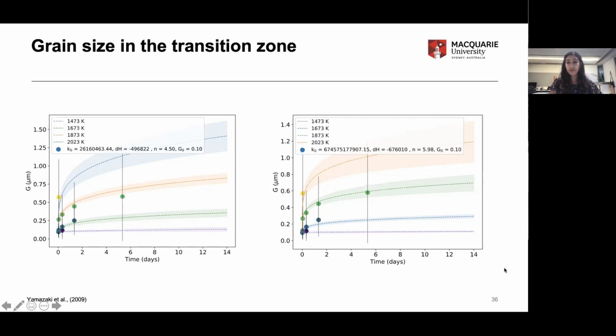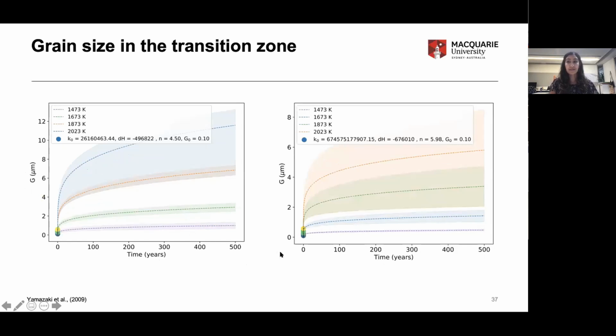For a period of 14 days, the data looks great. As soon as we start to extrapolate that out to 500 years, again, we have the same problem. Although the order of magnitude of the grain size isn't too different, we have no idea what that temperature and pressure is doing, and we're overlapping again just for a period of 500 years. So for people using these grain growth kinetics to try and understand things like mantle viscosity and the evolution of Earth over 4 billion years, we need to really constrain the kinetics before we start using them in models to predict mantle viscosity, for example.